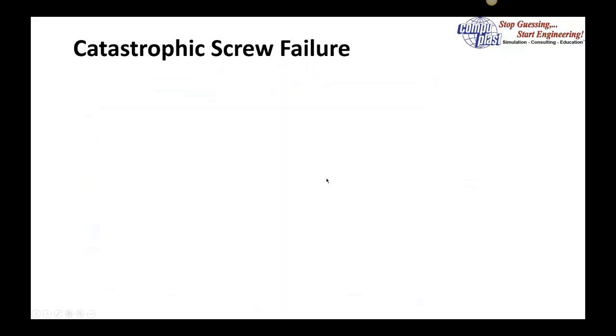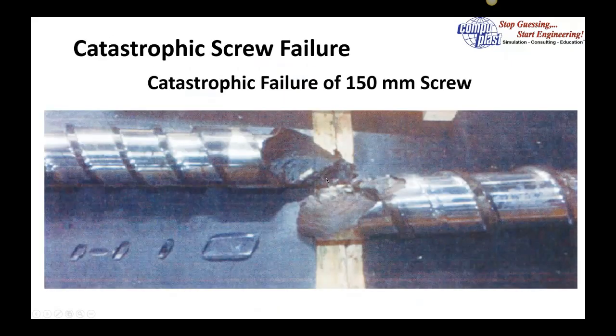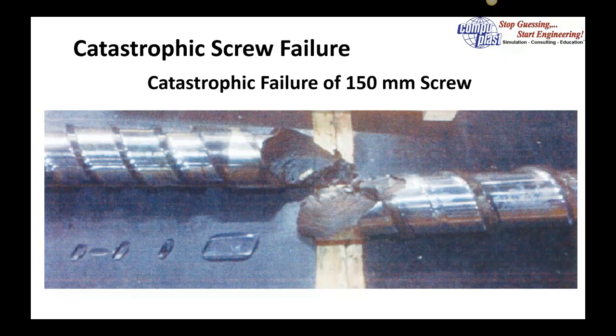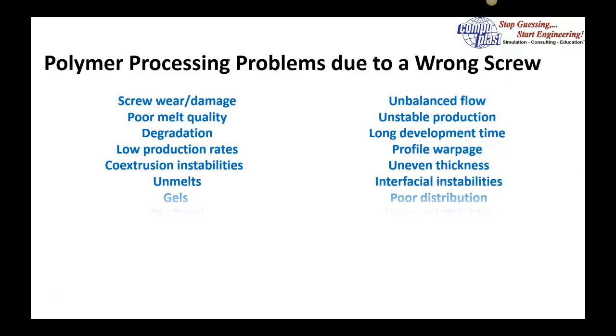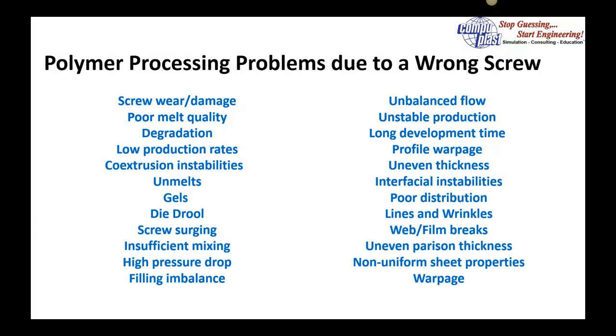The larger gaps result in increased shear heating and higher melt temperature. It's important to monitor the wear of your screw. Not understanding what the condition is of the screw in your barrel can also lead to catastrophic screw failure. In fact, there are many problems that can be related directly to having the wrong screw for the material you're processing.